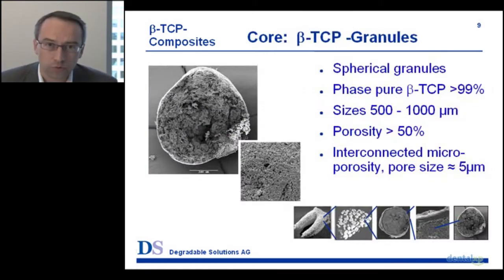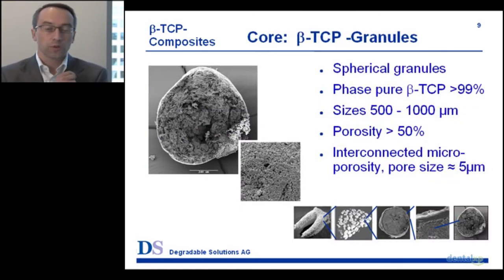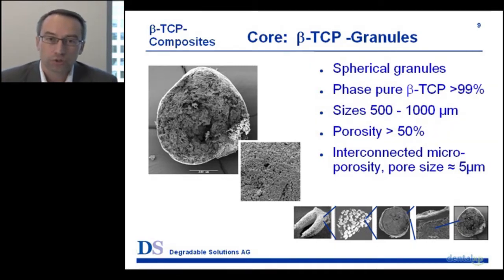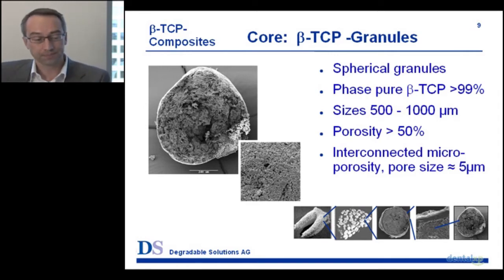So we started by creating a beta-tricalcium phosphate granule. We made a roundish granule, as you can see in the slide here, which has a porosity of over 50%. We made sure that we really have a phase pure beta tricalcium phosphate, so we know exactly what we are using and implanting. And we made sure that we have an interconnected porosity within the granules, which will allow the fluid exchange throughout the granules.